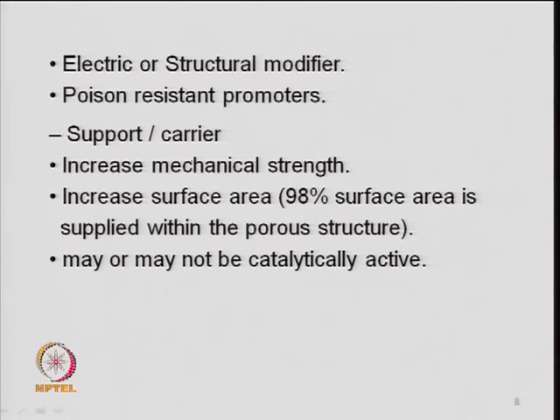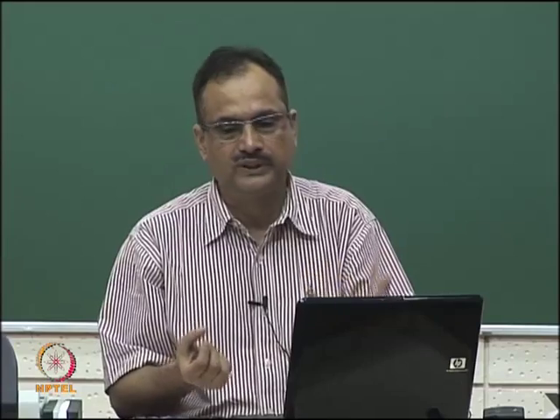There are other promoters — electric and structural modifiers. Sometimes a conductive material can be added to give different electrical or heat conductivity. Structural modifiers like graphite are added as a pore former — when you prepare the catalyst, a small concentration of graphite or wood cellulose material is added, and during calcination this gasifies and you get more pores or larger pores. These are known as pore formers.